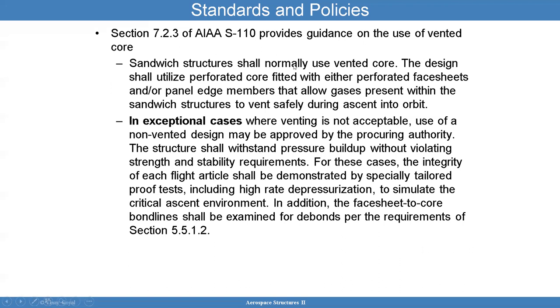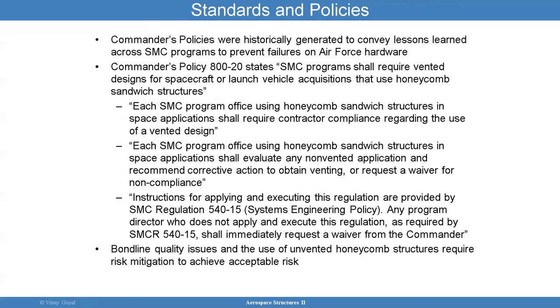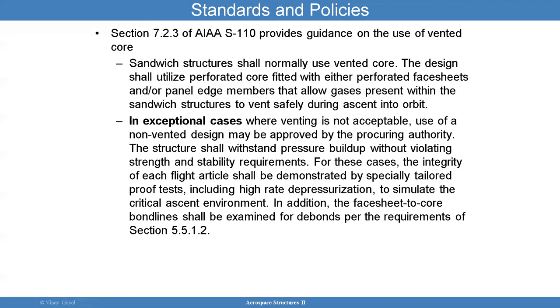If you look at AIAA S-110, which is a standard that governs structures used by spacecraft and launch vehicle designs, it talks about making sure that you vent the design. Sandwich structures shall normally use a vented design, utilizing perforated core fitted with either perforated face sheets and/or panel edge members that allow gases present within the sandwich structure to vent safely during ascent into orbit.